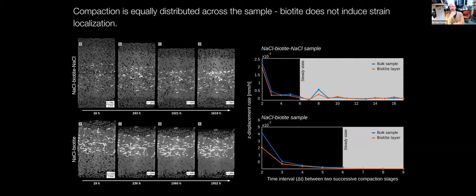Now, remember, we were thinking about stylolites, and we wanted to study pressure solution and how the sheet silicates essentially initiate strain localization into the formation of these distinct stylolite planes. And we wanted to see how the porosity works around that, how it has evolved. So here, much to our surprise, we found that if you wanted to localize deformation, or this bulk shortening, in here, any localization would essentially mean that this biotite bearing layer would have to take up more of the shortening, right?